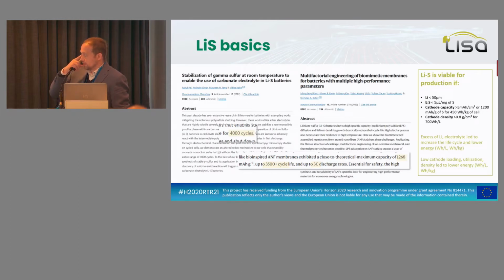What is important to take into consideration: recently in Nature, at the beginning of the year, I saw at least 2 publications claiming plenty of cycles for lithium sulfur. But what you have to take into consideration is what you have on the right, the format of the components that you will put in the cell. It means that if you want to reach something above 700 Wh per kg, you have to respect this KPI. And none of these articles respect it. So this is why you always have something different between what you see in the literature and what is really possible to be done at an industrial relevant level.